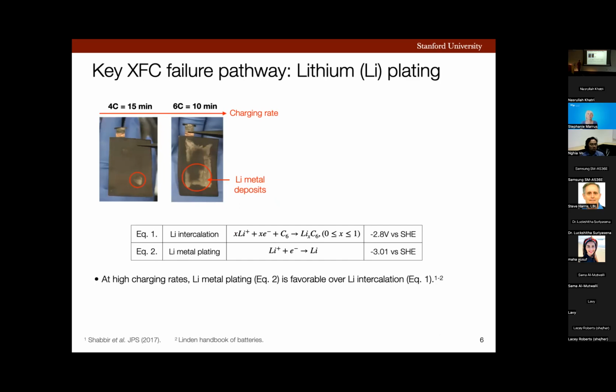Now, what happens at high charging rates is that lithium metal plating becomes favorable over lithium intercalation. And lithium ions, instead of intercalating between the layers of graphite, start plating as lithium metal on the surface of the battery anode. And if we look closely at the electrochemical potentials of the two reactions, you can see that they are pretty close to each other, and hence the competition between the two reactions. And fast charging creates favorable conditions for lithium plating to dominate.